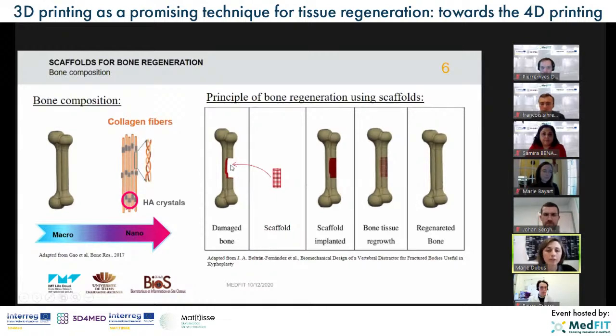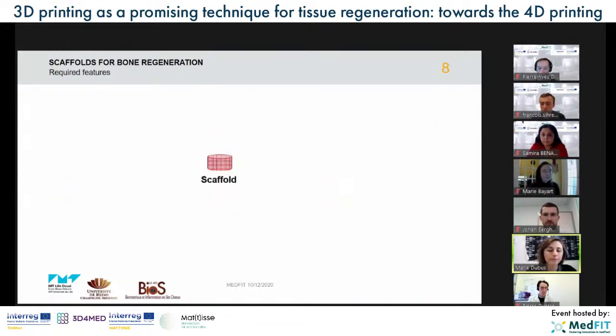To be used in bone tissue engineering, the scaffold is implanted at the damaged site to replace the missing bone, as long as necessary for the bone to regenerate. And then the scaffold is degraded while the bone is regenerating. That is why the scaffold needs to lure the original bone by mimicking it the best possible way. And in order to develop the best bone scaffold, we therefore have to respect strict features for the scaffolds.